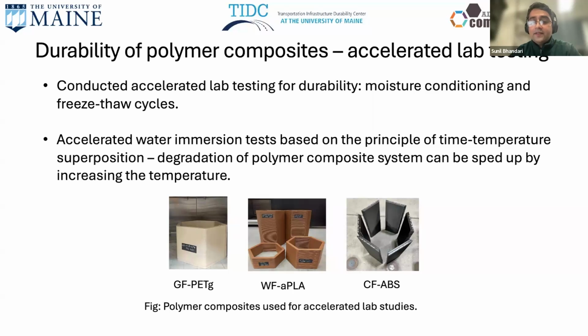So the assumption is that similar degradation will happen in a shorter period of time. So slow degradation over a long time is equivalent to fast degradation over a short time. So years of degradation in the field is simulated by exposing specimens in lab to similar conditions but at elevated temperature. So we did the accelerated testing for 3 different polymers: glass fiber reinforced PETG, wood flour reinforced amorphous PLA, and carbon fiber reinforced ABS.